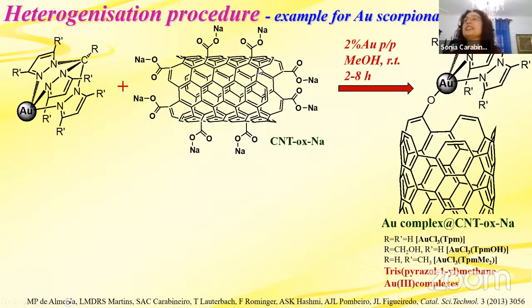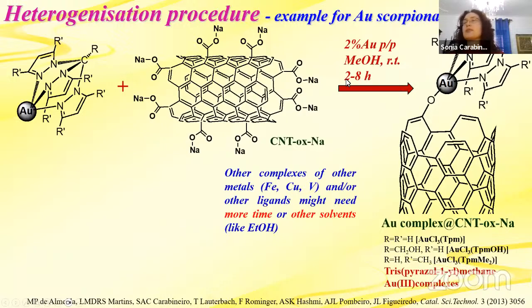So this functionalization, just as an example, was to have 2% metal in weight, and it was dissolved in methanol at room temperature, and it was a very fast process. From 2 to 8 hours, it could be totally dissolved. Of course, other complexes of other metals, like, for example, iron, copper, and vanadium, or other ligands, might need more time or other solvents, like ethanol, but here we could do it in methanol.